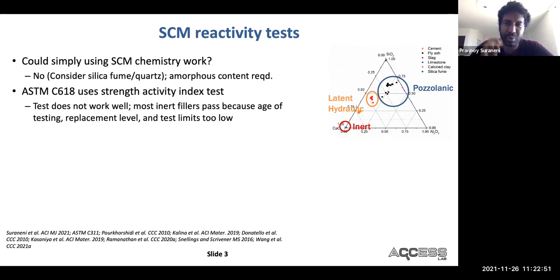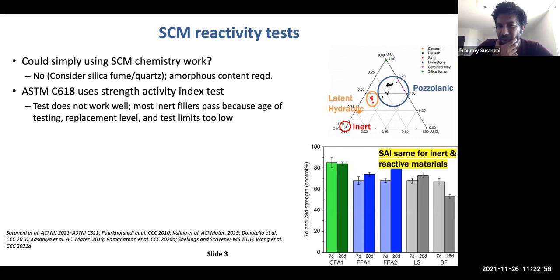The replacement level is too low. The test limit is also too low. I'm not going to go into details, but we wrote a paper about it, essentially showing that in a lot of conditions, you get essentially the same SAI for inert and reactive materials.